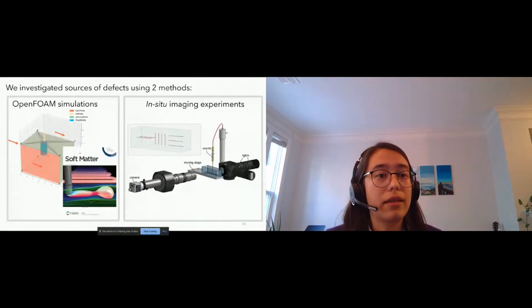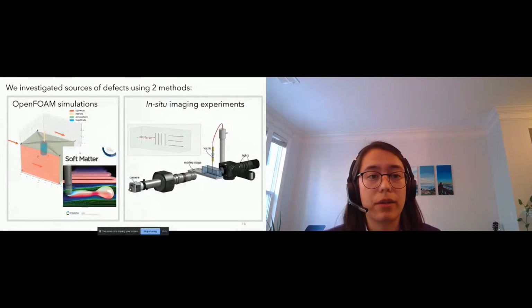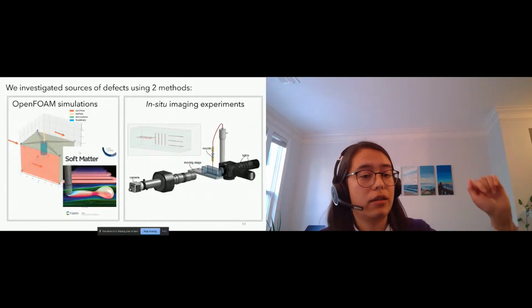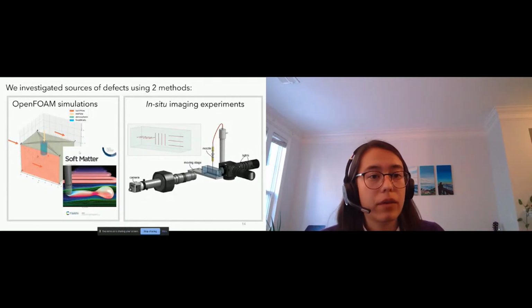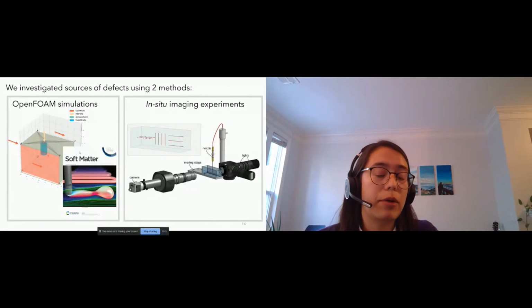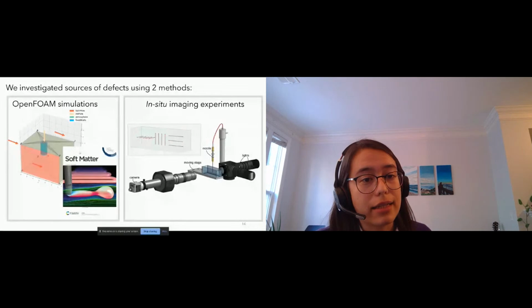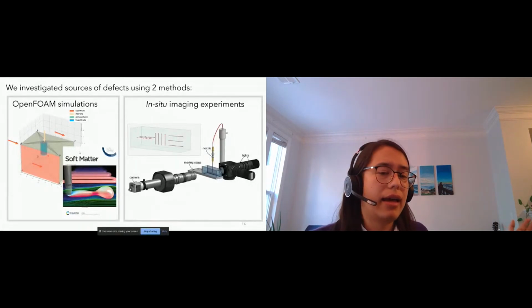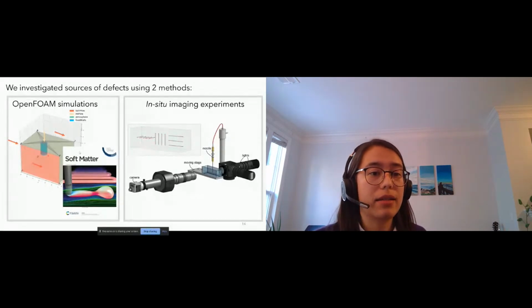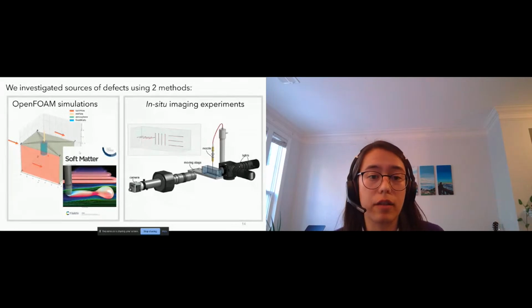We used two methods to identify these sources of defects. We used simulations and experiments. So these simulations were done in OpenFOAM, which is a computational fluid dynamics solver. So we imposed a pressure of ink onto a static nozzle, and then had a moving bath moving past it, and so that would extrude a single filament.